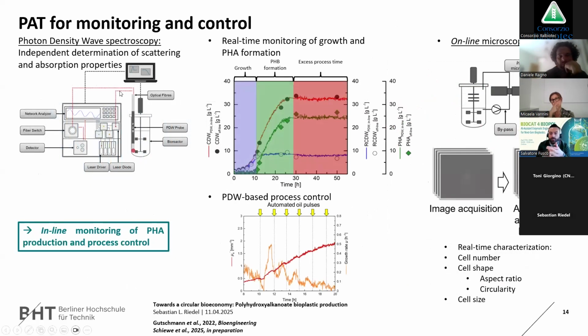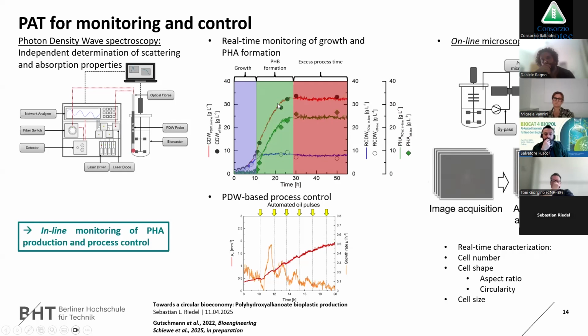What I said about the photon density wave: when you measure your culture or other samples in optical density, you cannot distinguish between absorption and scattering. By applying photon density waves, you can distinguish between that, so you get two signals - a signal for absorption, shown in blue, and a signal for scattering, shown in red. What we found out is that the scattering correlates perfectly with our offline cell dry weight, so the cells are scattering and the PHA inside the cells is scattering, but the PHA is not absorbing.